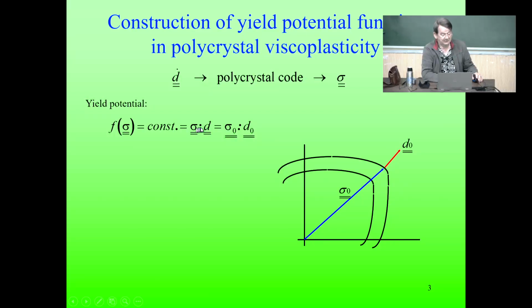When we multiply with the contracted product, this is basically the plastic work, or with the strain rate, it is the plastic power. So the plastic power should be constant along the yield potential. The plastic power in general is multiplying the stress with the strain rate, in the polycrystal stress and polycrystal strain rate. It should be constant, so we choose a reference value, which is a given sigma 0, D0 combination. This is the reference value.